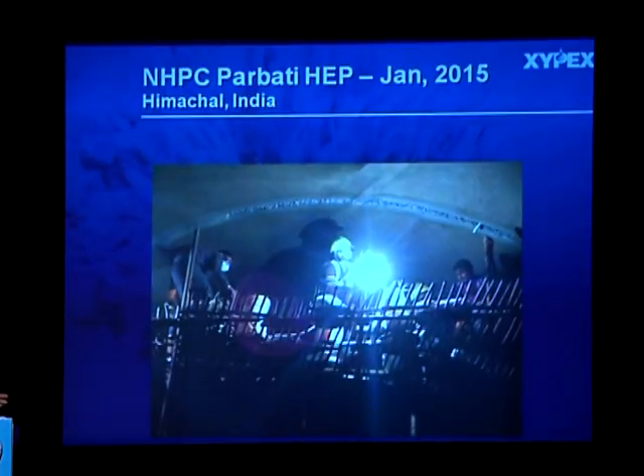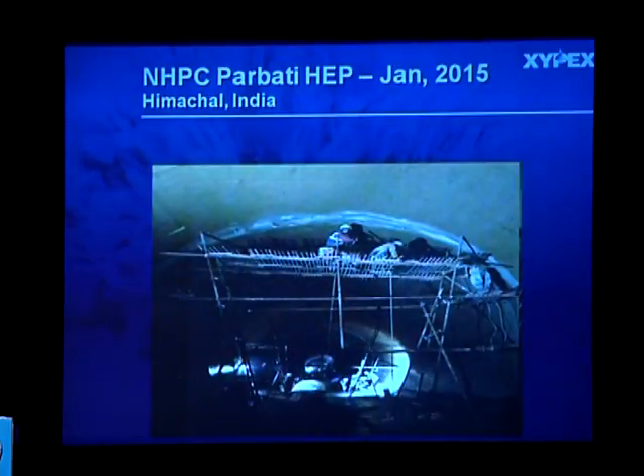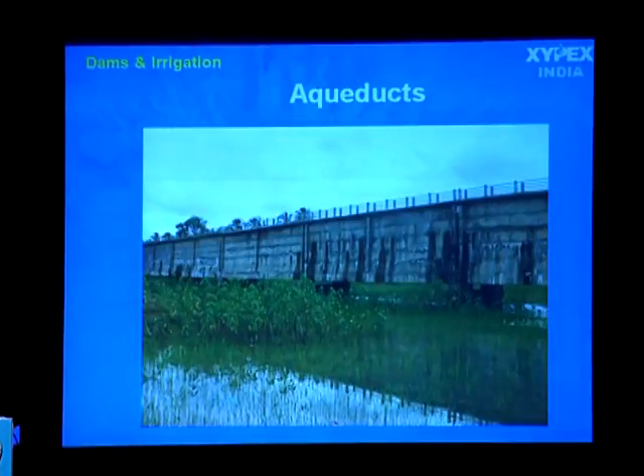In January 2015, last year, we treated part of a hydroelectric project in Himachal again, one of the NHPC projects. We treated the draft tube, and there was a loss of almost 10,000 LPM on a yield basis, which actually got reduced to 1,000 LPM after the treatment of all these curb joints and construction joints, and we also used our material for grouting some of the weak and honeycomb areas in the structure there.